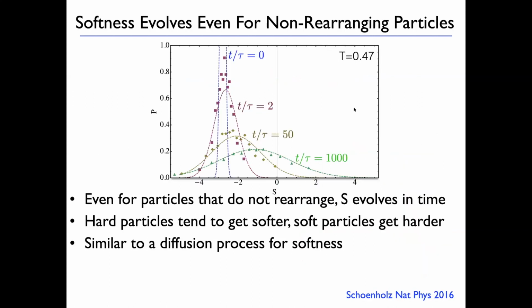But now you can make the following simple observation, which is that even for particles that don't rearrange, their softness changes with time. Why? Because other particles nearby can rearrange, and that changes the local neighborhood, the local g(r), the pair correlation function for this particle, the structural environment of this particle. What happens is that if you start with a delta function at a given softness, looking only at particles of given softness at time 0, and see how their softness evolves in time, over time that distribution will revert to the mean. It is very close to Gaussian, and it spreads out in time, much like a diffusion process. That actually does quite well in describing this.